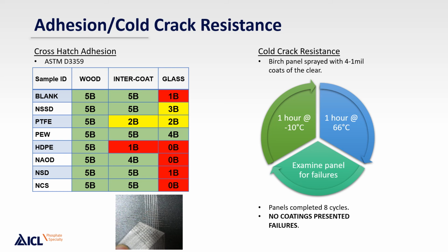Interestingly, intercoat adhesion on those substrates was seen as failures for some of the additives, so I think that again points to some of the drawbacks with formulating with waxes at times. So the PTFE and HDPE saw a significant loss of adhesion when looking at intercoat. And many of these wood coating applications require multiple coats. Often 3 to 4 coats of these UV products are applied on a finished product.